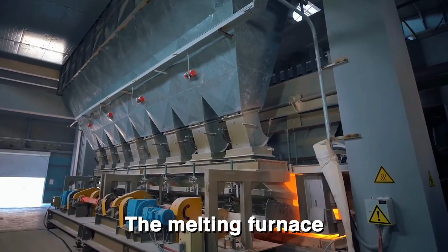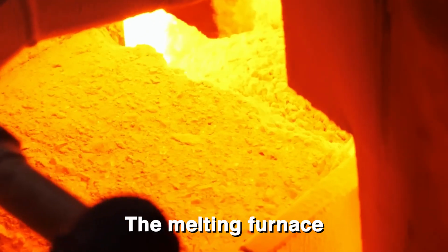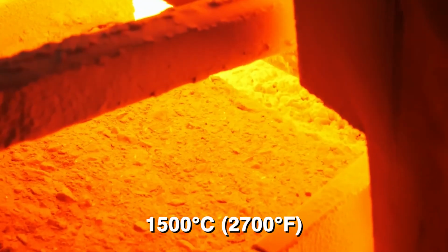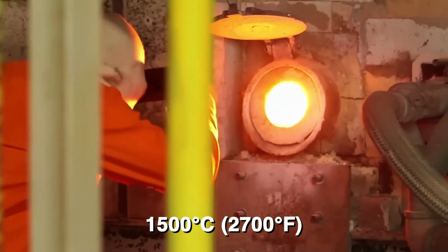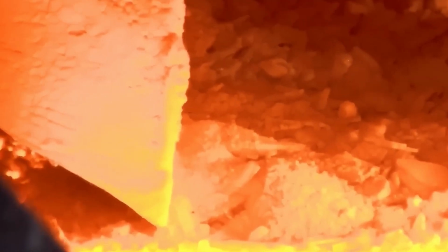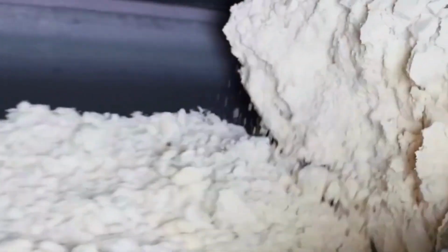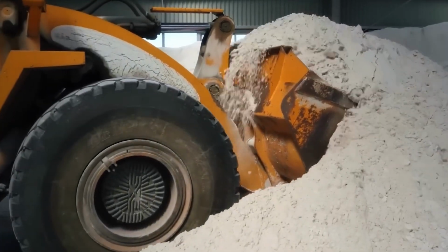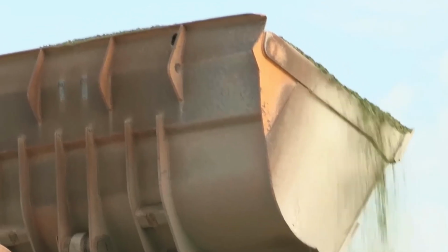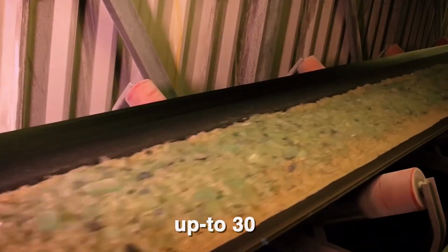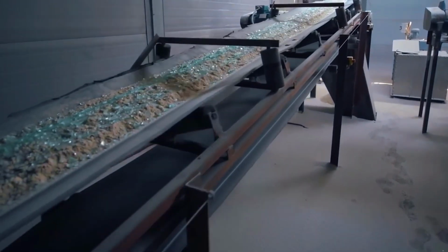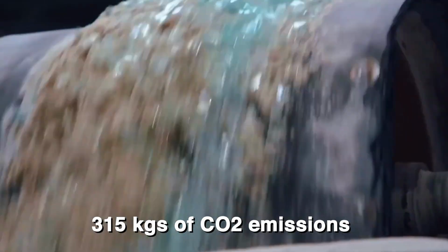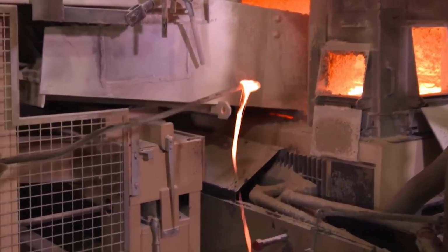The melting furnace. These furnaces are industrial giants, glowing at over 1,500 degrees Celsius, about 2,700 degrees Fahrenheit. The cullet is mixed with virgin raw materials, silica sand, soda ash, and limestone, in exact ratios to restore the glass's chemical balance. Adding recycled cullet not only saves raw material, but also reduces the energy required for melting by up to 30%. That's because cullet melts at a lower temperature than raw sand. Every ton of recycled glass saves about 315 kilograms of carbon dioxide emissions and nearly a ton of natural resources.